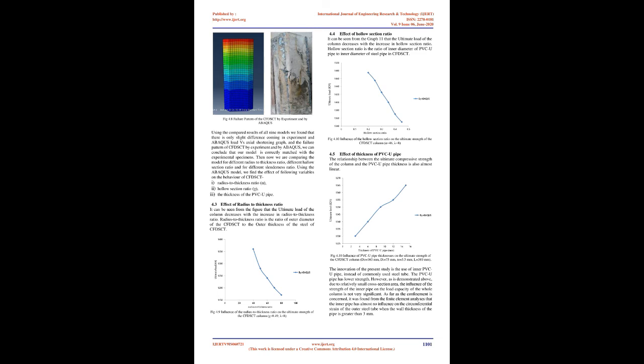The former was due to the combined action of axial compression and internal expansion of concrete, which may lead to the welding failure, local or global elastoplastic buckling failure of the steel tube. The latter was due to the crushing failure of concrete material, which, in turn, may lead to the failure of the outer steel tube. Fig 4.8 Failure pattern of the CFDSCT by experiment and by ABAQUS.